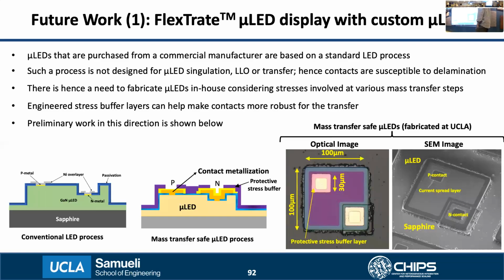So here, I'll quickly show some preliminary work that was done in this direction. You see here on the left side, a conventional process where the LED is first defined and then the contacts are essentially evaporated on top. In the middle, you see the new mass transfer safe micro LED process, where after the contacts have been fabricated, a stress buffer, which is using a combination of silicon oxide and silicon nitride, is essentially deposited and patterned so that some of it overlaps with the contact area,